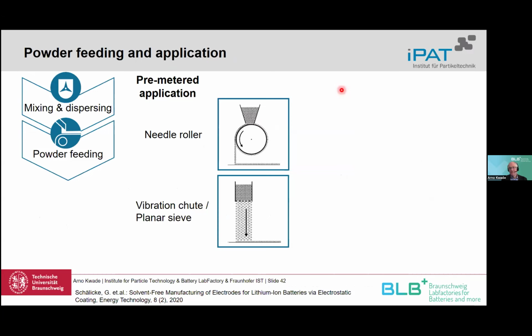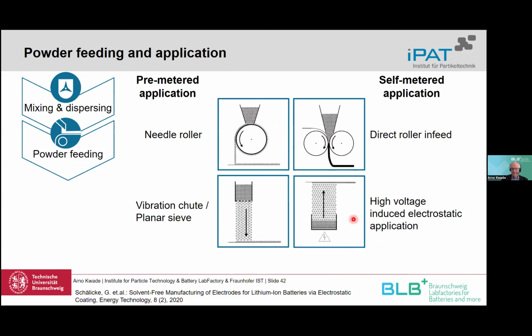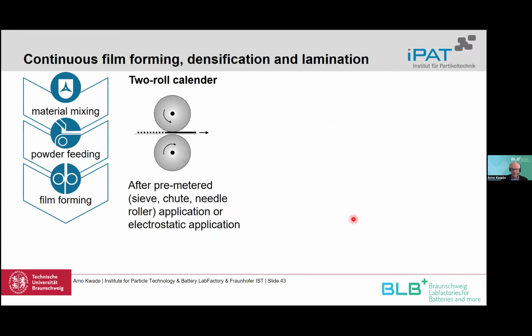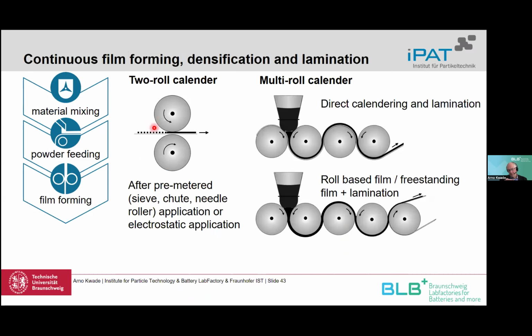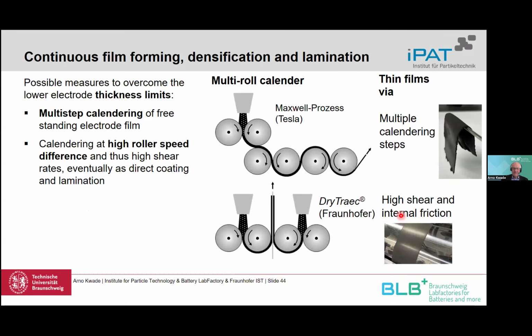Now coming to the dosing process, which will also be shown by Hans Schneider. And you see we have maybe a pre-meter dosing, which is not so typical today, but also direct roller feeding, which is the most common one. And what I wanted to show you here is that we have a two-roll calendaring process, where we dose it onto the conductive collector, or we have several steps through the calendaring machine. And I think there are two production processes which are typical. That's the Maxwell process, where we have a freestanding film or roll connected film, and we need several steps to come to the right thickness, and then we transfer it onto a substrate.